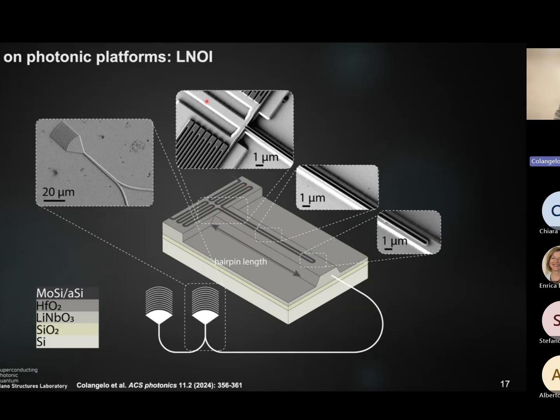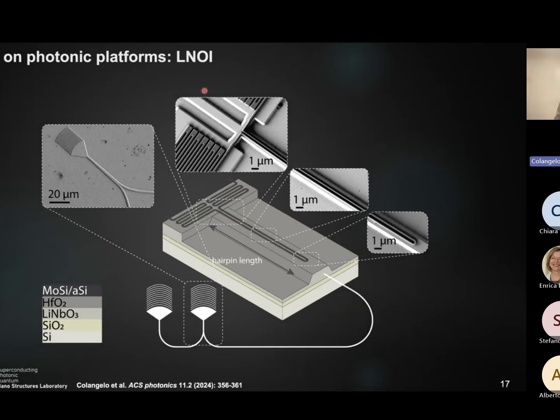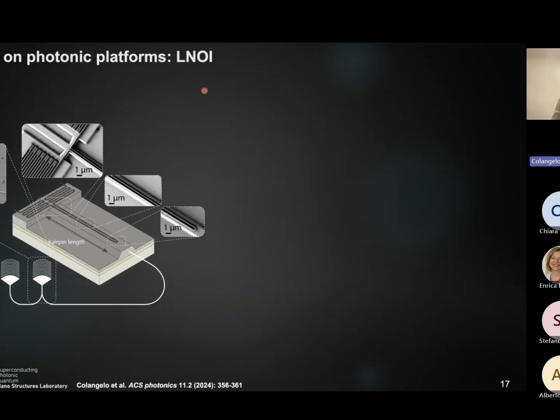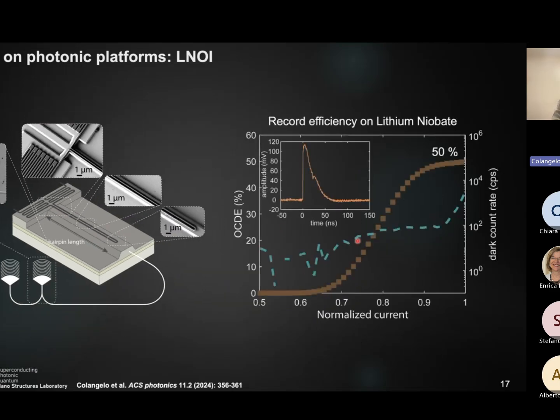Here is a demonstration on lithium niobate, which is a promising platform for photonic applications. By testing again the efficiency and the jitter, we are able to get 50%, which is actually a record, again, on efficiency on lithium niobate for this type of integrated devices. Another problem of this approach is that this is one device. However, we said at the beginning that we will need tens and hundreds of devices.